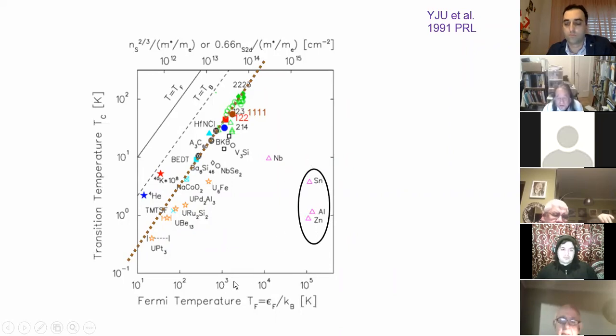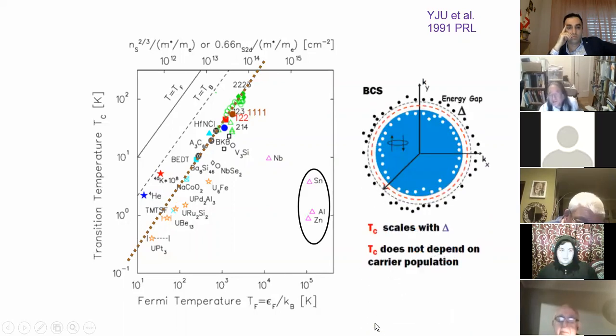So you see BCS superconductors have very high Fermi temperature, a high charge energy scale, but the transition temperature for superconductivity is low. Compared to that, these new superconductors have a rather small Fermi temperature, but very high transition temperature. The ratio is very different from these BCS superconductors. So this is again showing that these new systems are probably fundamentally different from these old systems. And as I mentioned, in the case of BCS superconductors, we would not expect TC to be related to this Fermi energy. Actually, you are seeing that these three different simple metals, zinc, aluminum, and tin, have about the same Fermi temperature, but superconducting TC is so different. That is the case you expect for BCS. In the new superconductors, these two parameters are related, and that's why you see this linear line.